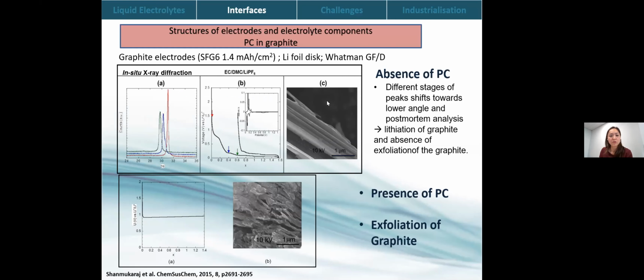So in this case study, we look at a half cell that is built with lithium foil disc and graphite electrodes with a loading of 1.4 milliamp hour per square centimeter with a Whatman glass fiber separator. With the in situ X-ray diffraction in this electrolyte of EC/DMC with LiPF6, we see that in the absence of PC, we can see the lithiation of graphite. And here, the different colors of the arrows correspond to the different peaks that we see on the X-ray diffraction, showing a gradual lithiation of the graphite. And here we can see in the SEM picture that there is no exfoliation of the graphite.